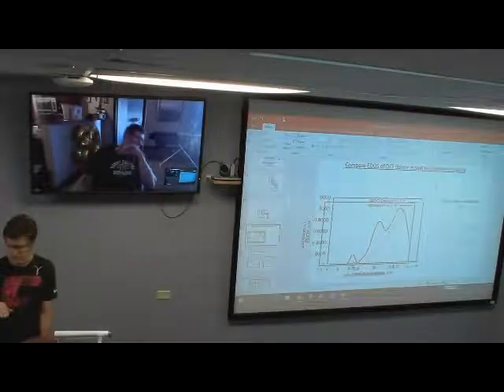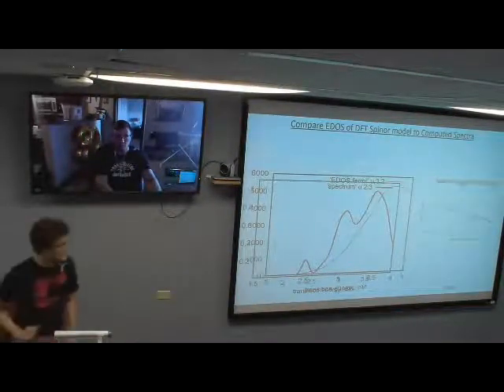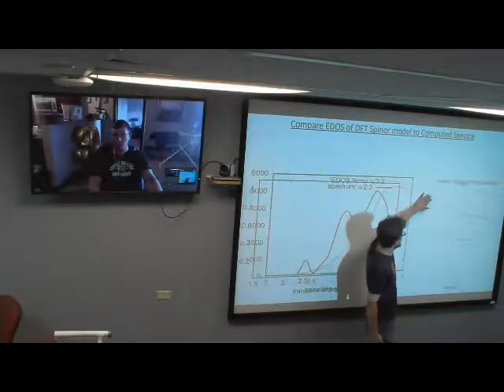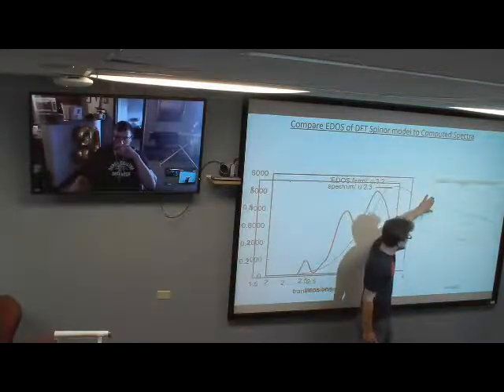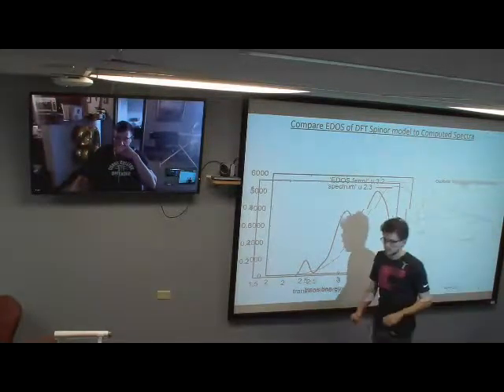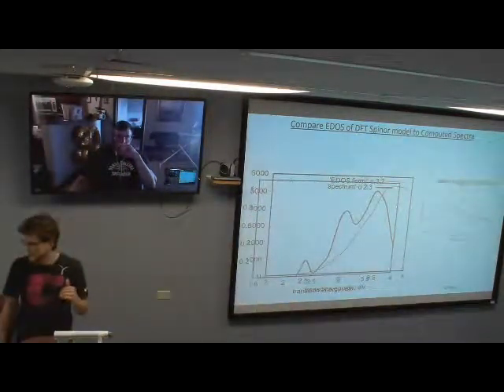Another thing I noticed is this plot on the right is basically the oscillator strength versus transition energy for the DFT. Does this fitting take care of all transitions or only the brightest ones? It looks like a very repeatable trend. They all go on a line. Yeah, so this is a log plot. So this here is like the lowest energy, HOMO-LUMO. And then the higher the energy you go, the oscillator strength decreases pretty exponentially.